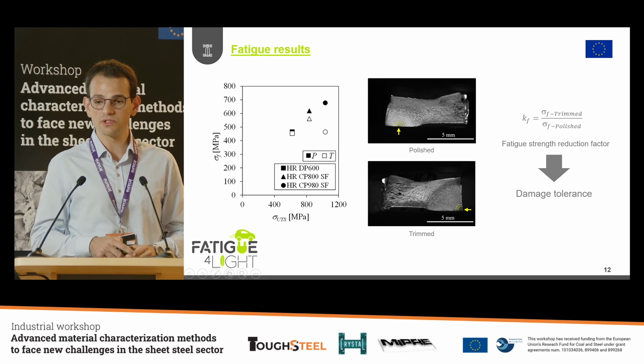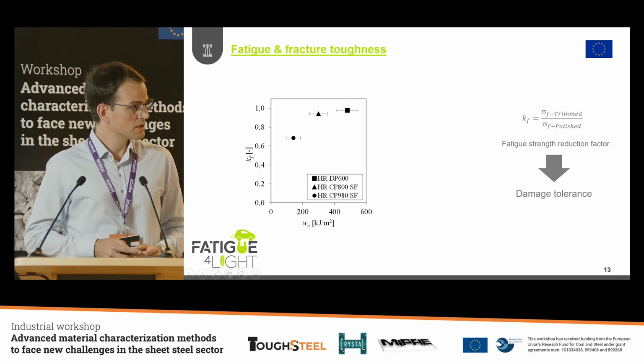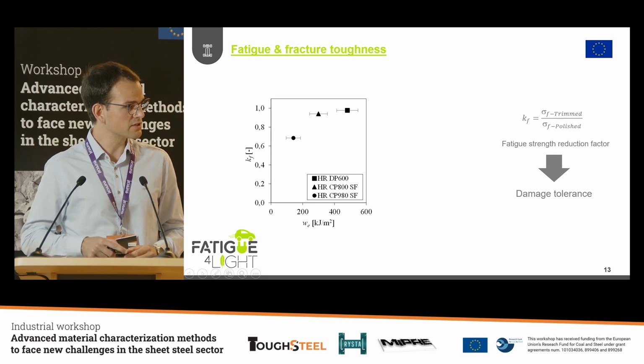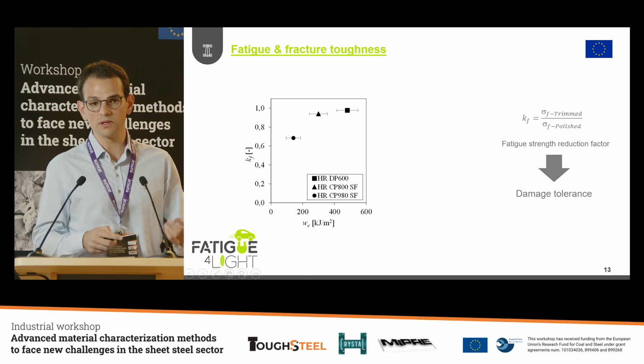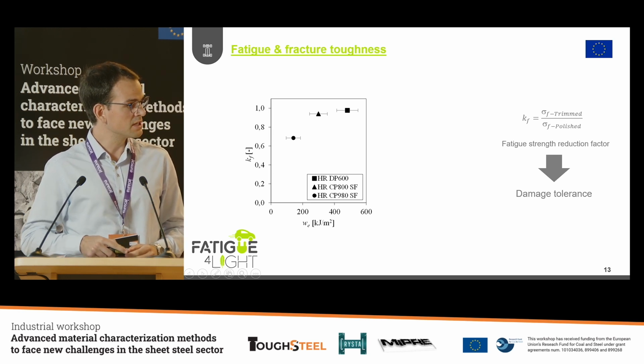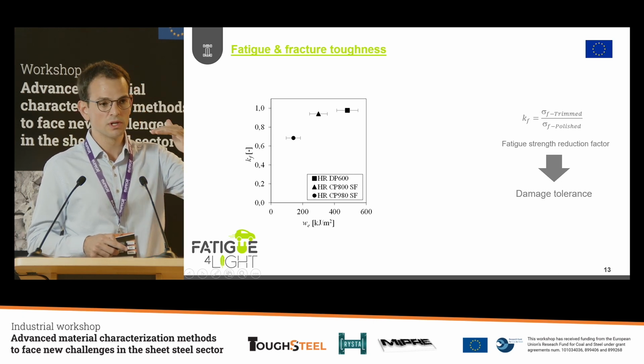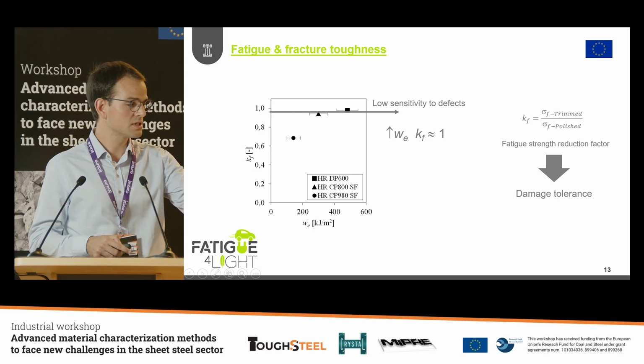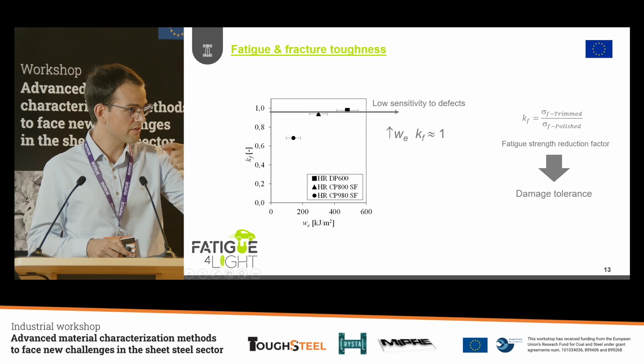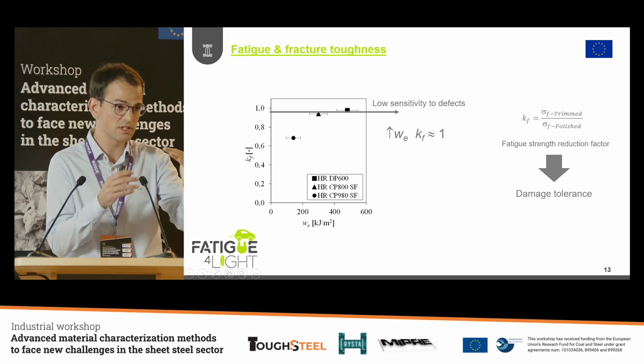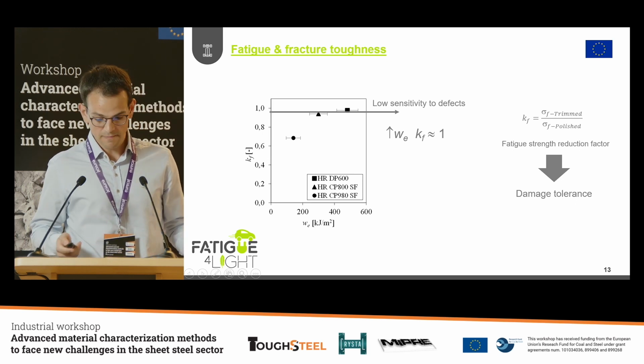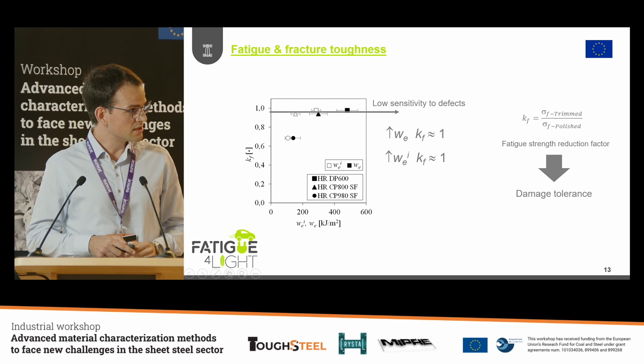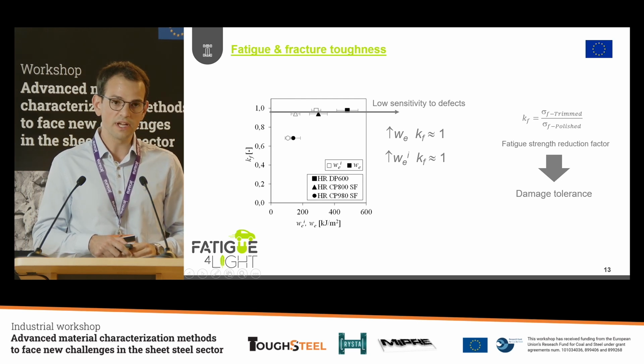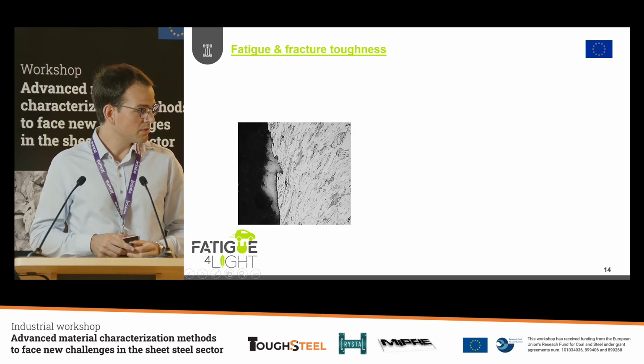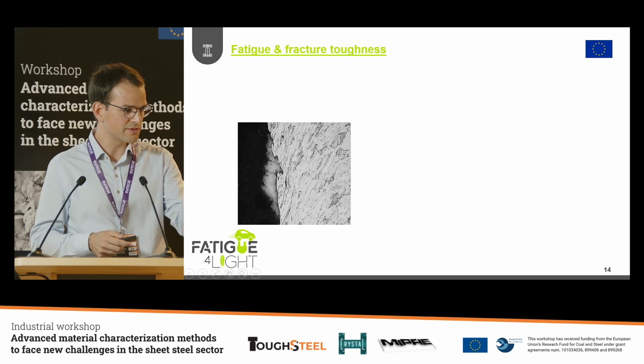And this fatigue strength reduction factor is related to the damage tolerance of the material. So if we plot this fatigue strength reduction factor against the fracture toughness values that we obtained with the essential work of fracture test, we can clearly see that at a given point we are achieving a kind of plateau. So the materials that present high fracture toughness also show a low sensitivity to the defects. So this KF factor, this fatigue strength reduction factor, is almost 1. So the fatigue resistance between the polished and the trimmed specimens is almost the same. This trend is also maintained for the energy required to initiate a crack. But why can we relate these two properties, this fatigue behavior and also the fracture toughness behavior?